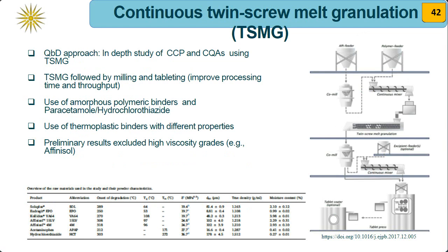This is another study where a quality by design approach was used in order to study in depth the critical processing parameters and the critical quality attributes using a twin screw melt granulation process. For the purpose of the study, a complete ConsiGma line was used, followed by milling and tableting of the obtained granules. The authors used amorphous polymeric binders and paracetamol and hydrochlorothiazide as the model APIs. The use of thermoplastic binders with different properties was one of the key elements of the study, and some preliminary results excluded high viscosity grades.